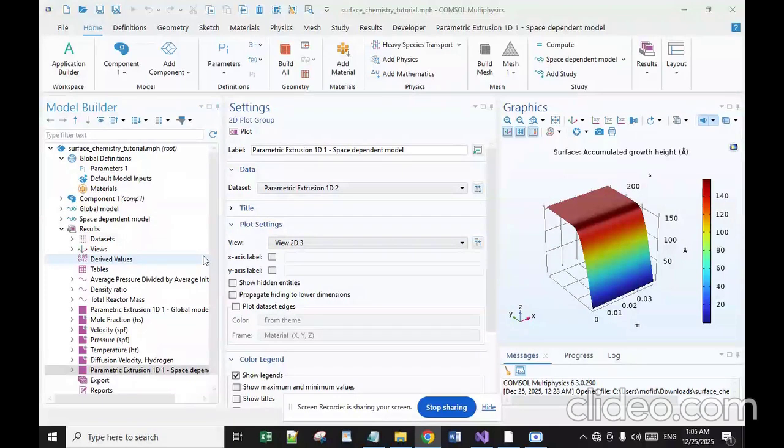During the growth of graphene, the role of methane is to provide a carbon source. The role of hydrogen is to provide hydrogen atoms to corrode amorphous carbon and improve the quality of graphene. But excessive hydrogen atoms can also corrode graphene. As a result, the integrity of the crystal lattice is destroyed and the quality of graphene is deteriorated. Therefore, by optimizing the flow rate of methane and hydrogen gases in the growth process, the quality of graphene can be improved. And use of catalyst.